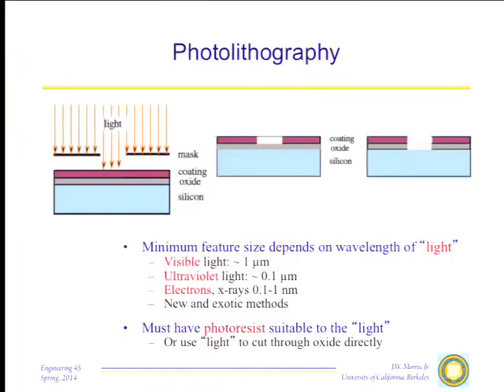We have talked earlier about the Czochralski method and ways in which we could grow large, almost perfect, high purity single crystals. And that's done routinely in plants all over the world right now. Huge pools of electrical quality silicon can be turned out, and that is the template on which we write microelectronic surfaces. The way that we write the microelectronic surfaces is the following. You take your little silicon chip, you coat it with an oxide. Now I need to locate the regions that I'm going to dope with various solutes. The way that I do that is to coat the oxide with a photosensitive coating.